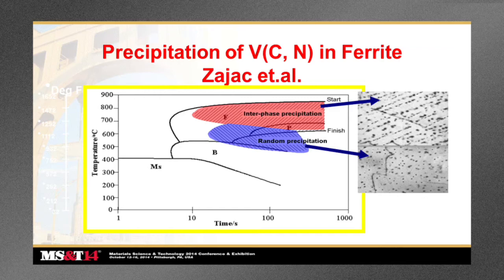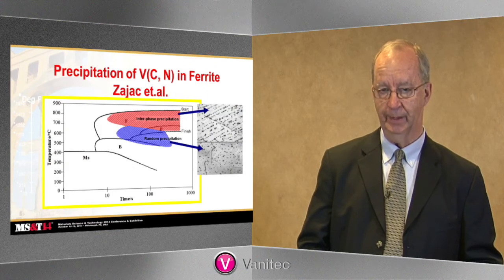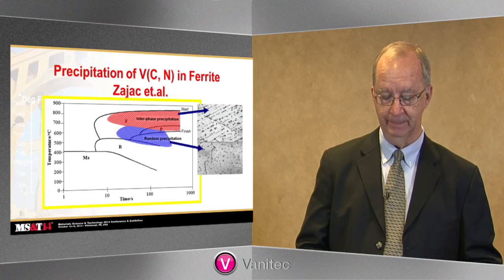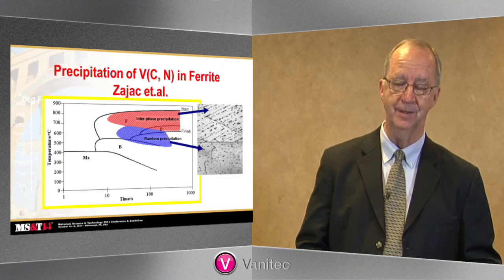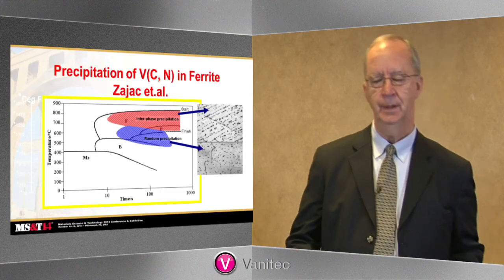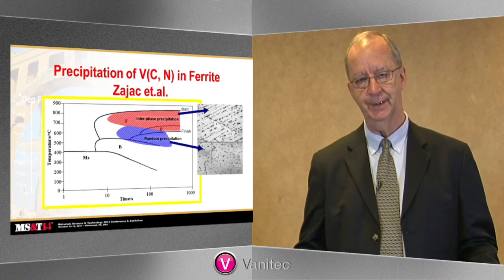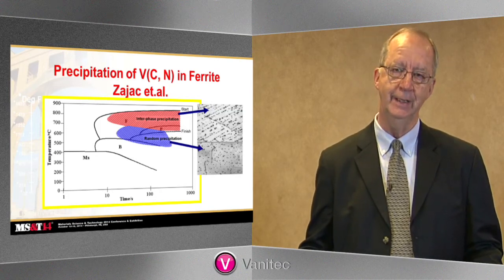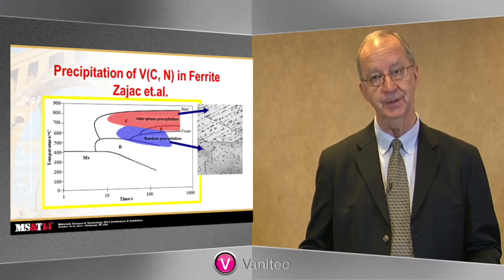However, looking at this curve, it does remind us of a couple of things. One is that precipitation in the austenite, that is, prior to reaching this transformation line, up in this zone, does not contribute to strength. And the second is that strengthening does occur at a relatively high temperature. And there is a temperature below which this precipitation of vanadium carbonitrides will cease, and you no longer get any effective strengthening if it has not precipitated at the appropriate time. Typically, most researchers looking at production kinds of processing times and temperatures find that anywhere from 50 to 70% of the vanadium will precipitate if there's ample nitrogen available.